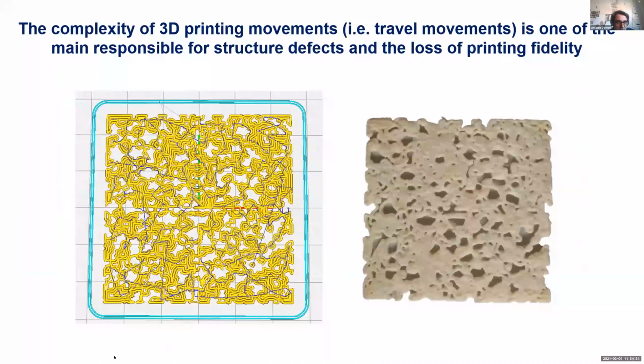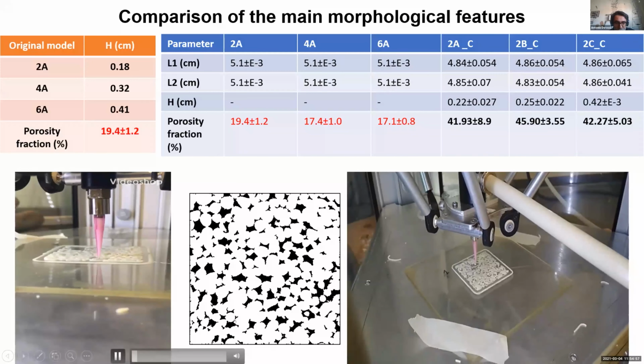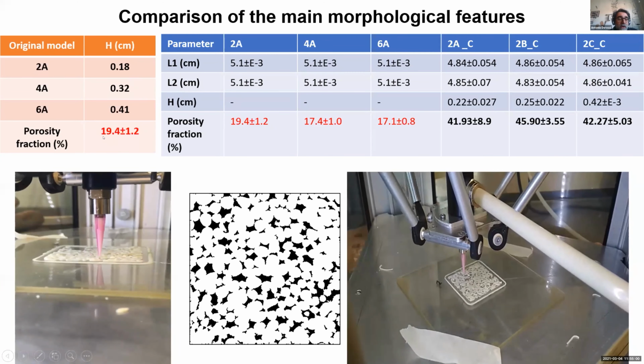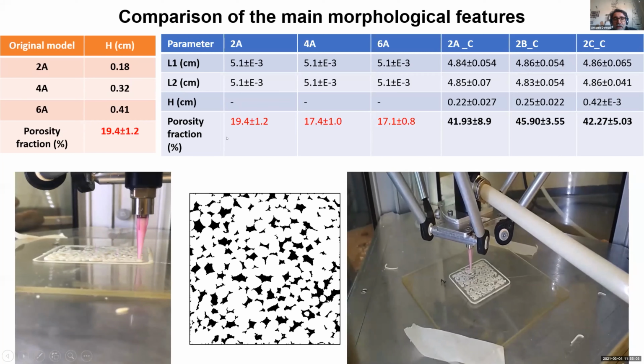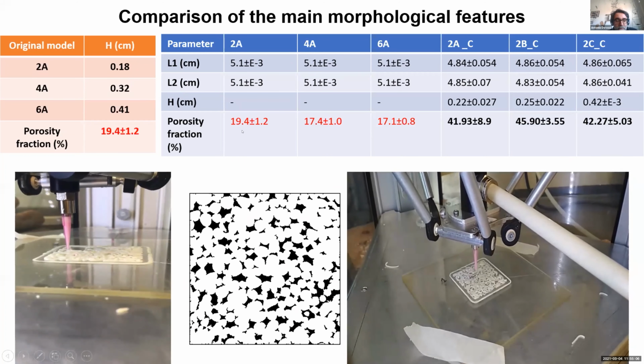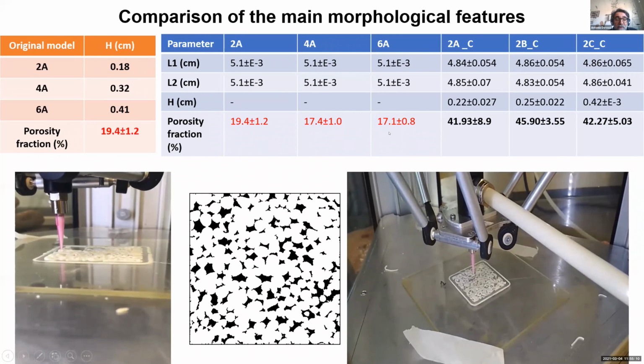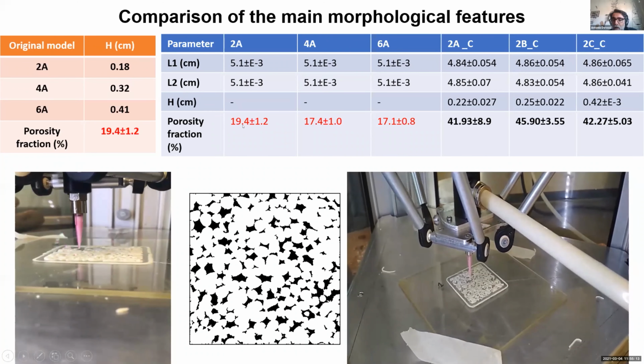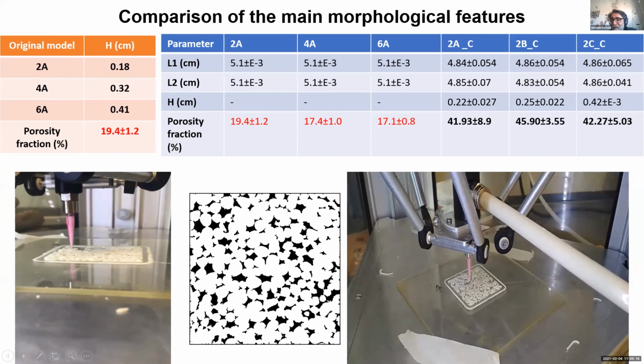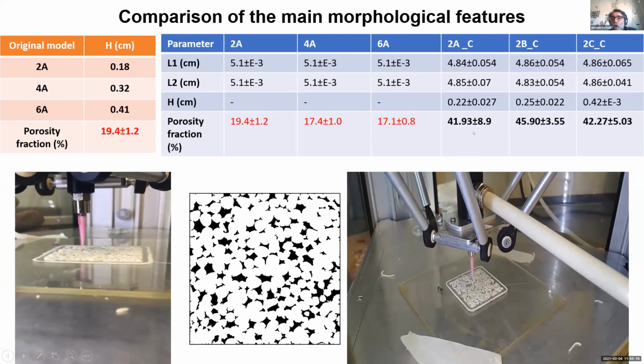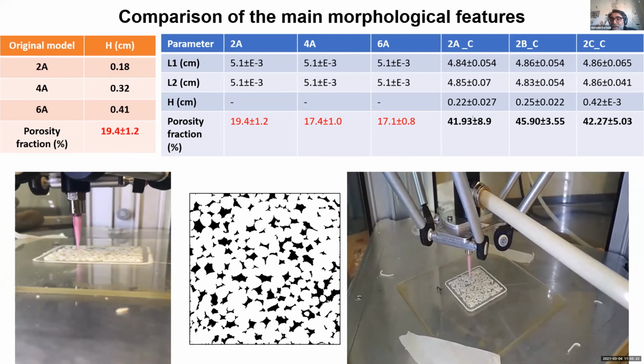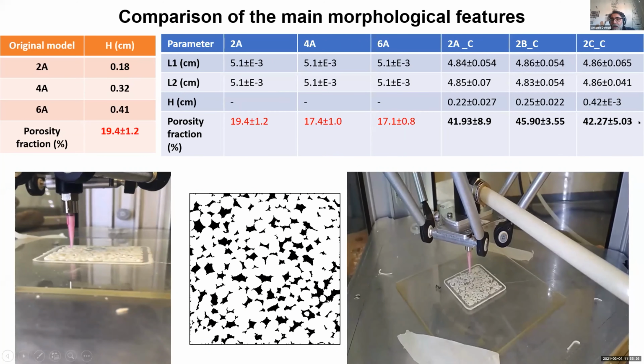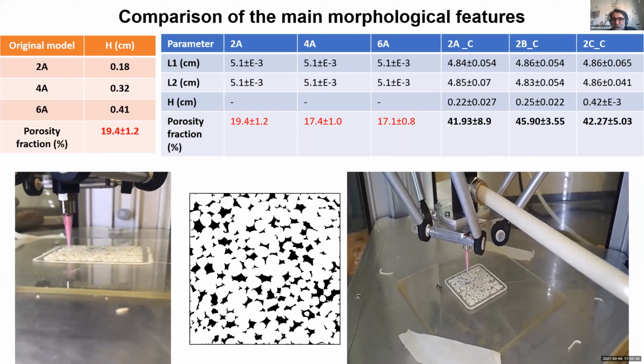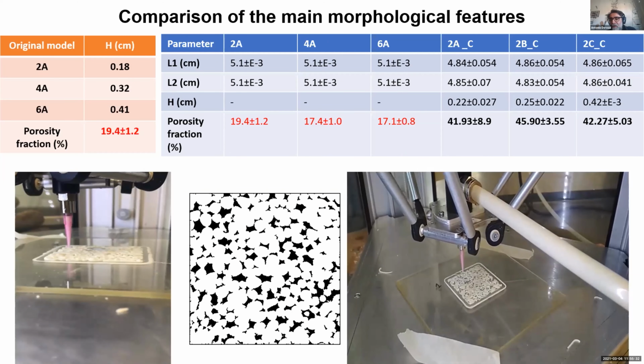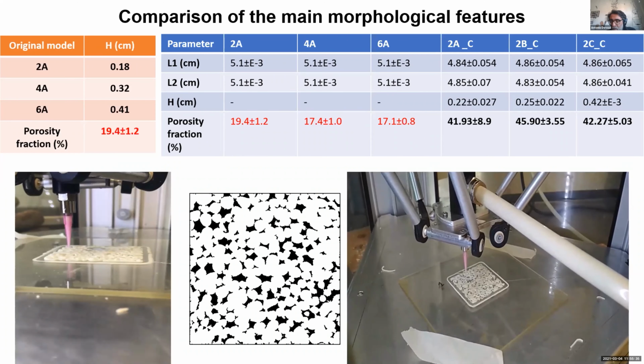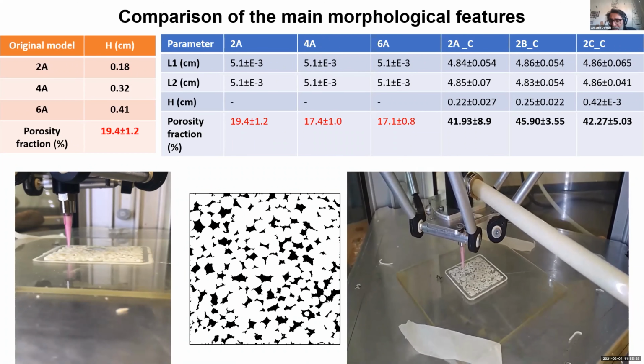Okay, these are two videos just to show you the movement of the printing. The porosity of the original model was more or less 20. These are the porosity fractions of the raw material before cooking. We obtained a satisfactory capability to replicate the model. And then after cooking in the oven, 180 degrees, obviously we obtained a really impressive increase in porosity, because during cooking in an ordinary oven and during dehydration, what we obtain is the formation of new pores and new fractures.